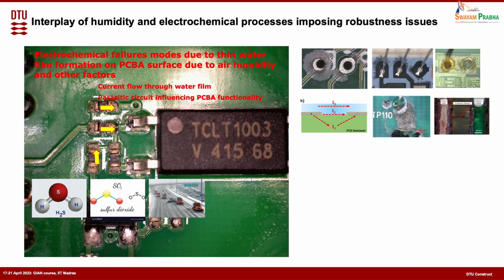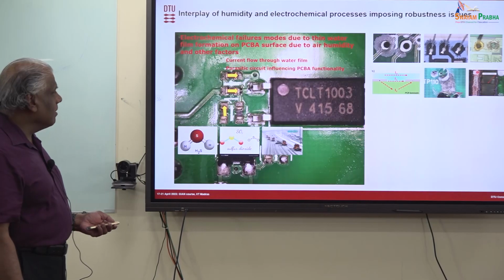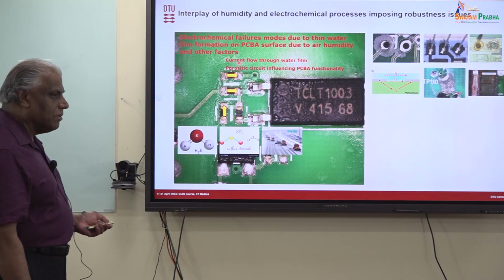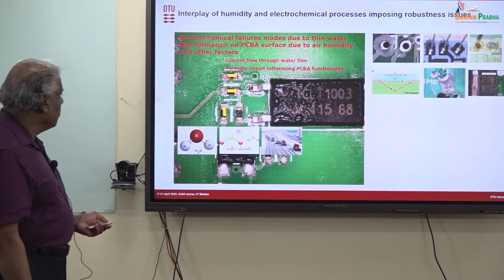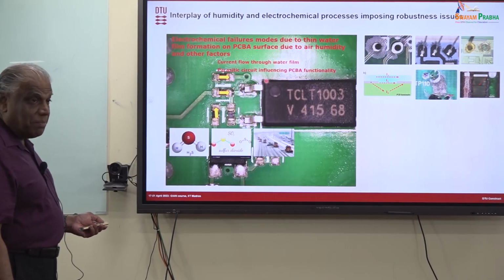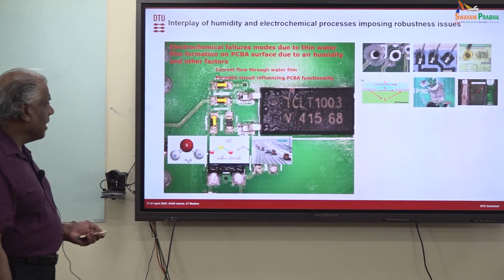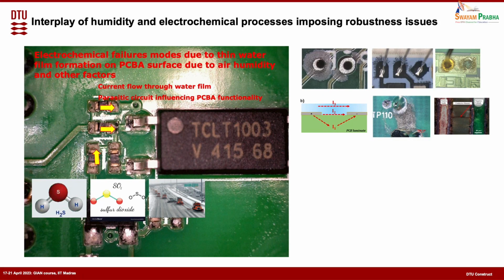This is another type of failure which you also saw in my front slide, called electrochemical migration. That means that when you have this anode and cathode, metal from the anode will dissolve, and because of the high bias, that metal will go and deposit on the cathode, and then it will make a growth like a dendrite, and then you get an electric short like that. So that's a very serious failure, because within a short time it can create an electric short, and then you have functionality issues.